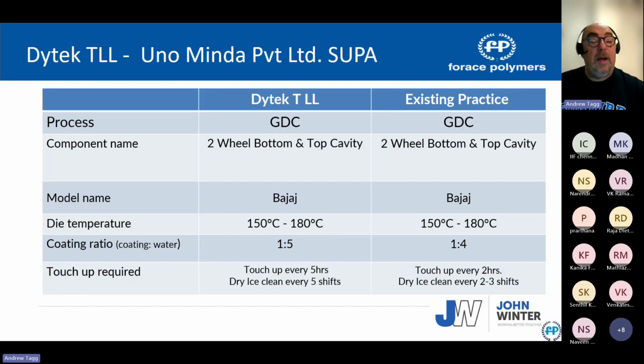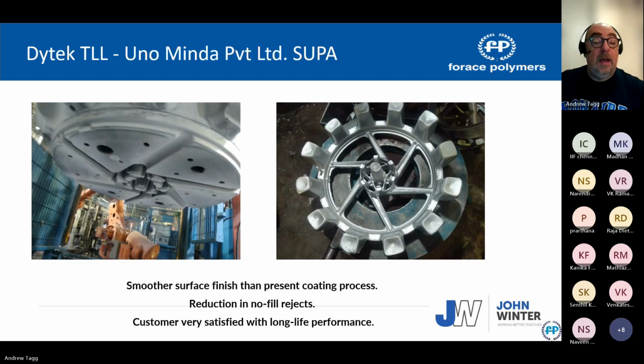So here's an example at Minda. It's a Supra, a Bajaj motorcycle wheel. You see that we've touched up 1 in 5 hours compared to touch up 1 in 2 hours. You can see there's a top die, and again, this is gravity, and you can see the risers all the way around here, with a big reduction in no-fill defects. He had a lot of no-fill in this center, this little center rib here and on these arms. So we reduced the no-fill defects.